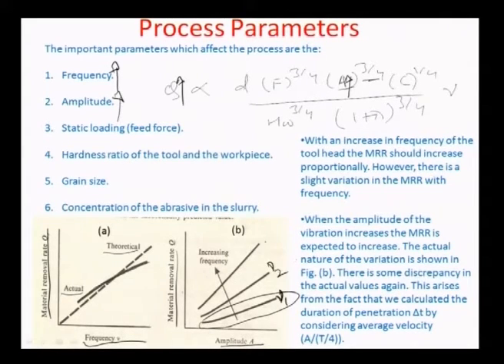And supposing the operating frequency keeps on varying between, let us say, nu1 to nu3, where nu3 is greater than nu1, you can see that there is a double effect. One is the effect because of amplitude, and another is an overall increase because the frequency domain in which you are operating, and mind you, frequency is proportional to the MRR here, is also increasing. So as you increase the frequency, the overall material removal rate, different for different frequencies, would have a linear increase with amplitude. We have already studied the feed force aspect, where you saw that there is a grain crushing effect, and some other trends that can be useful are those related to what would happen, for example, with increasing amplitude and feed force.